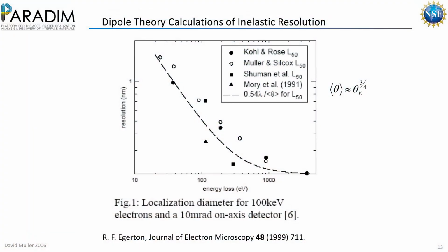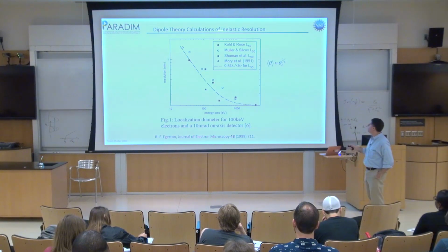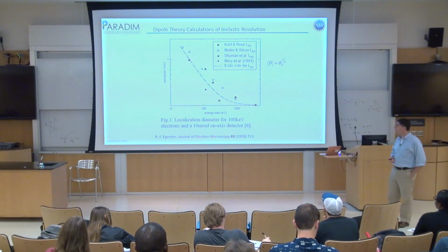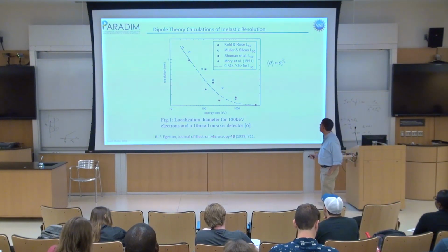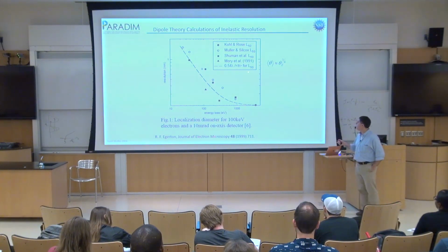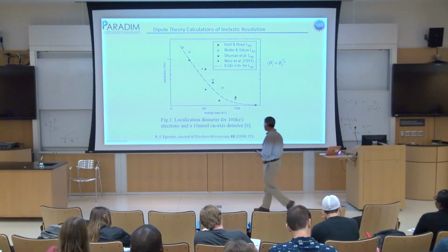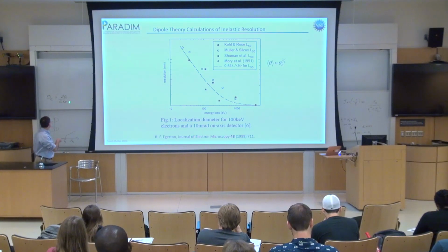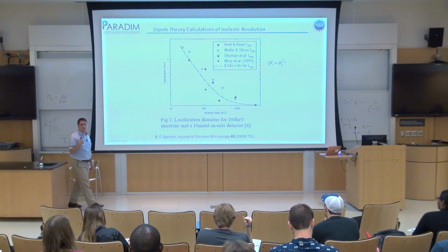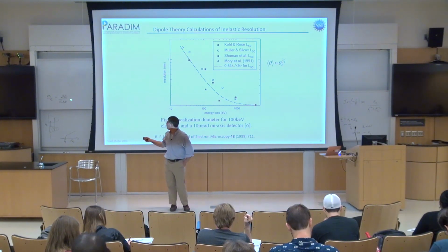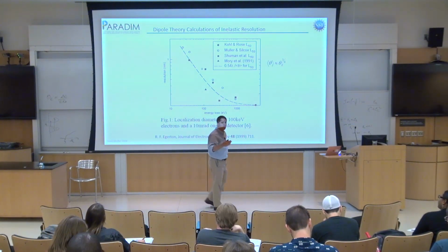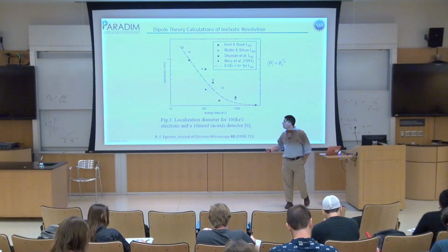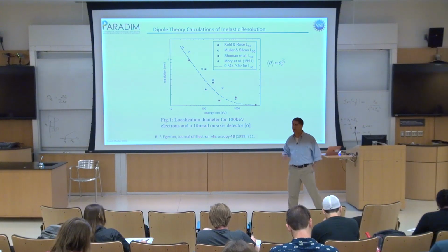So this is the normal analytic theory that you would use for estimating a spatial resolution by EELS. The quick rule of thumb is the characteristic angle, which comes from the scattering theory. If I wrote it out, it would just be theta_E = delta E over 2 E0. It's a nice dimensionless parameter that describes the typical angle you'll scatter through for an inelastic scattering event with an energy loss delta E and a beam energy E0. It more or less comes from conservation of momentum in the small angle approximation. So you use that as the angle that characterizes the Lorentzian profile of the scattering.